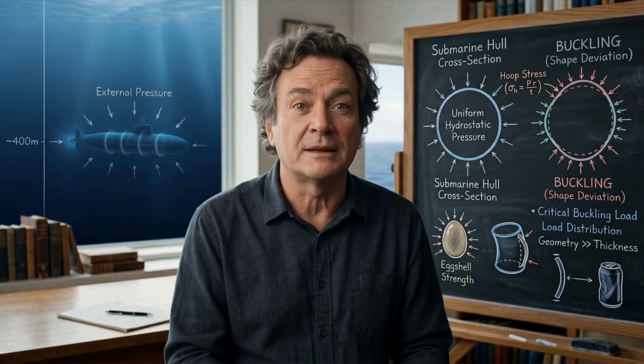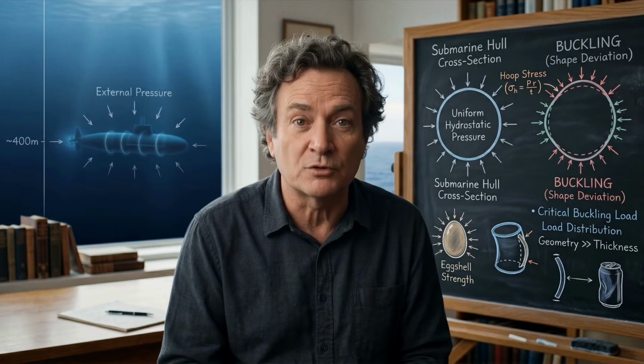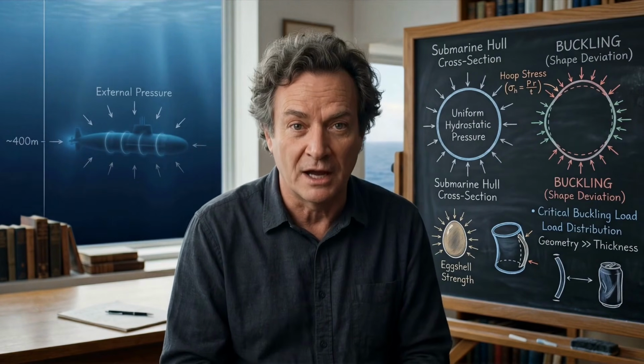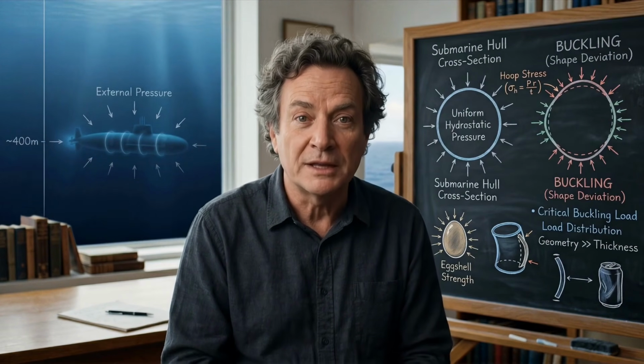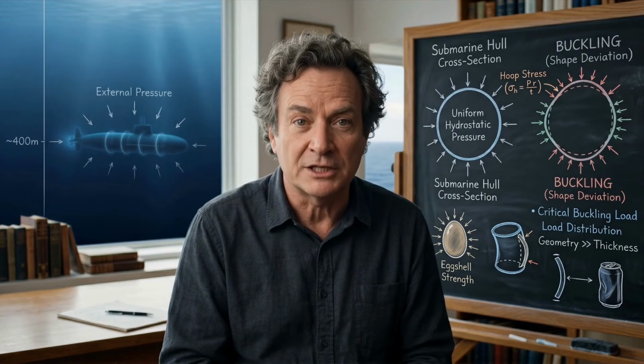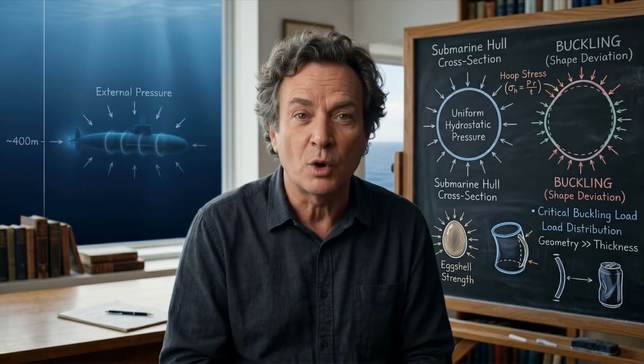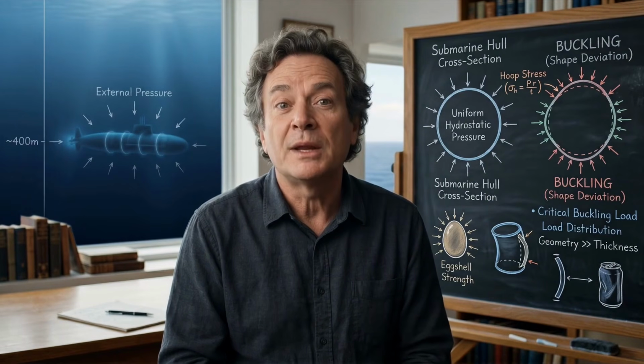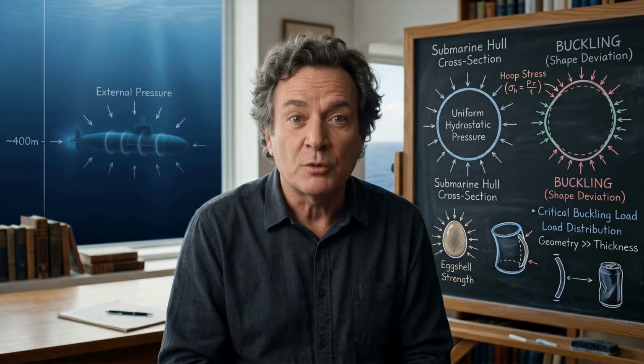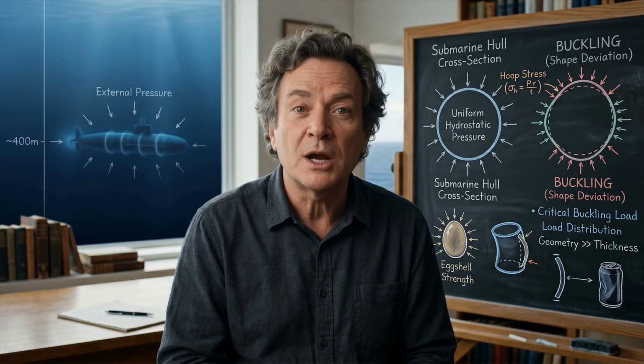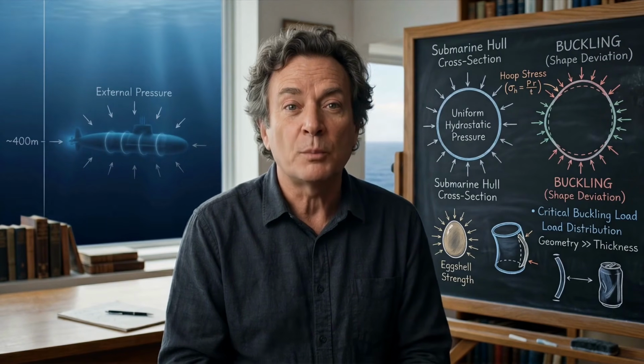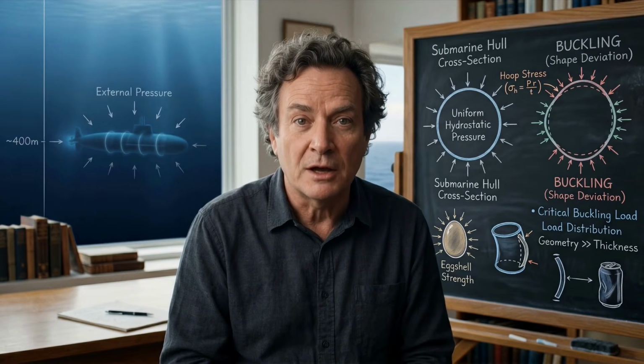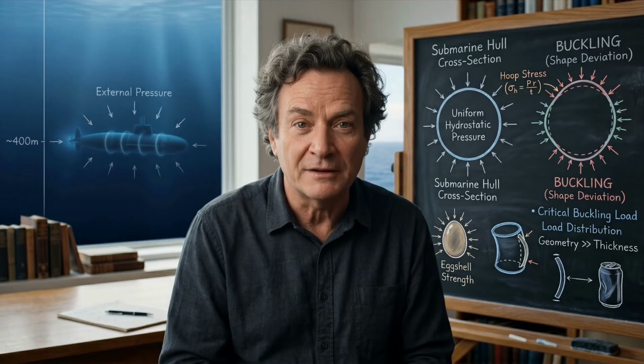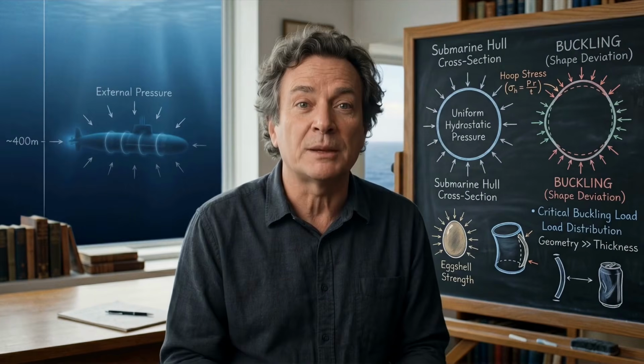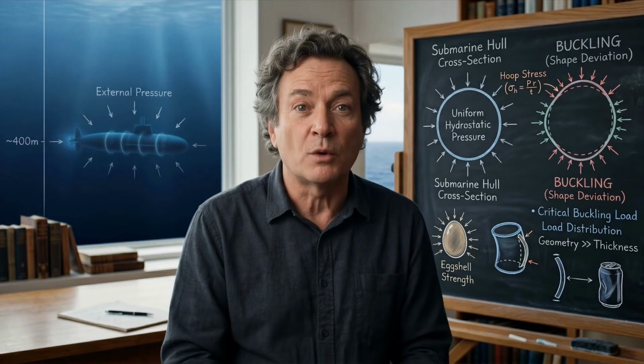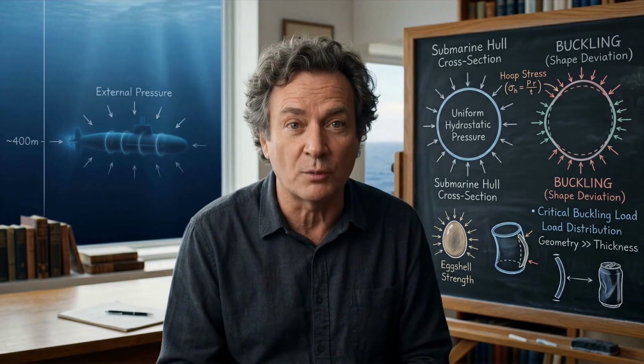What they discovered, sometimes tragically, is that hulls could fail at stresses well below yield through a process called fatigue. Fatigue is what happens when you apply a stress repeatedly, cycling between loaded and unloaded states. And over time, over thousands or millions of cycles, small cracks initiate and grow, even though at no single moment does the stress exceed what the material should be able to handle. Submarines dive and surface repeatedly. Each dive cycle subjects the hull to a full pressure loading and unloading, repeated hundreds of times over the life of the submarine. The hull must not only survive each individual dive, it must survive the accumulated fatigue of all the dives across its entire operational life.